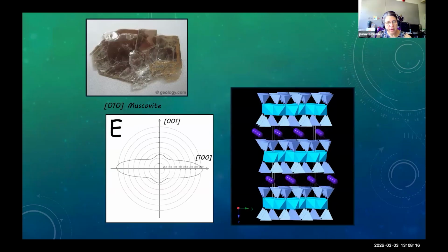And if you want to think about this from a more intuitive framework, I like to start with muscovite. You can think about the muscovite structure. It's made of sheets of octahedra with tetrahedra on either side. And if you had mineralogy, you know that the tetrahedral bonds are very strong. And so we have a structure that's highly anisotropic. We have sheets with very strong bonds in the plane, and then they are separated by much larger atomic sites where we can put big cations.